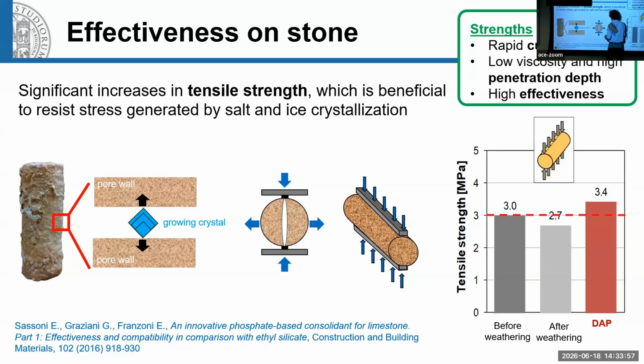So we performed the test on cylindrical specimens of stone by the so-called Brazilian test. You apply a compressive load in this direction, which results in a horizontal tensile strength. And as you can see here, we started with a certain type of stone, we performed some artificial aging to induce microcracks, and then after treatment with DAP, we obtained an increase in tensile strength. So in this case, it was a positive result.